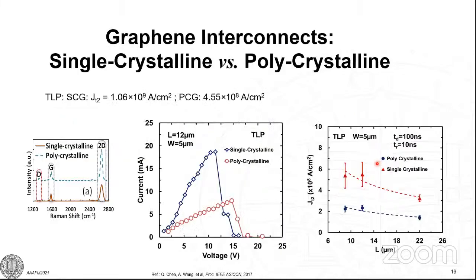Now, one last thing I want to mention is you can always improve the materials. What we show is the device made of polycrystalline graphene versus single crystalline graphene. So the poly one is over here, and the single crystalline graphene is over here. If we extract the current handling capability in terms of the current density, you can see clearly the single crystalline graphene is much tougher than the polycrystalline graphene device over here.